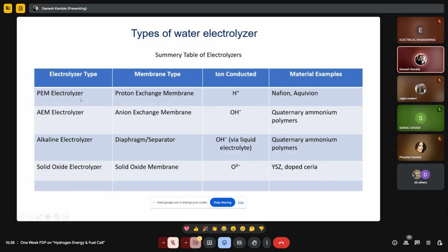So in this PEM electrolyzer, a proton exchange membrane is used, which carries or migrates H+ ions, and generally a Nafion or aquivion membrane is placed between two electrodes. In an anion exchange membrane electrolyzer, an anion exchange membrane is used, which migrates OH- ions, and this membrane is synthesized from quaternary ammonium polymers.